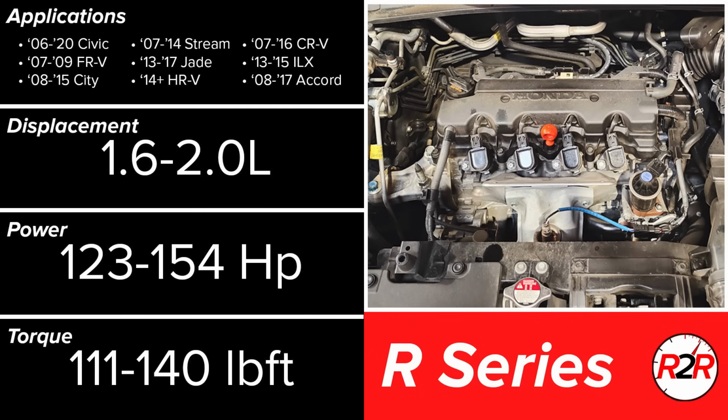The R-Series is very much an engine with two different stories. Early models are worth avoiding, while the later ones are respectable. Every R-Series is fully aluminum, but the units made between 2006 and 2009 were the victim of a manufacturing error. Each engine block was cast aluminum, meaning that molten aluminum was poured through a sprue into a die mold where it would then solidify into the engine block's design.